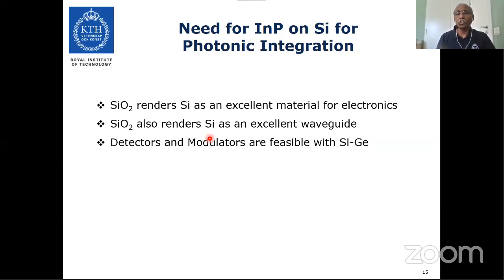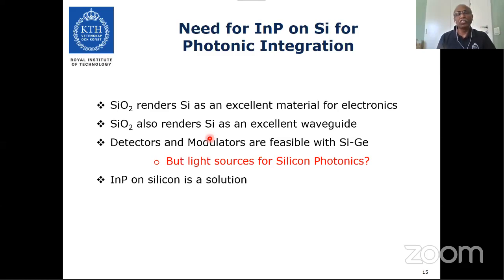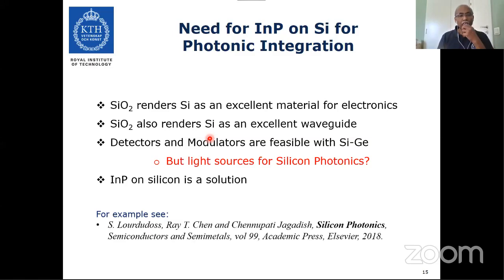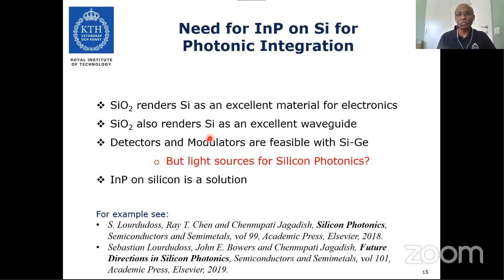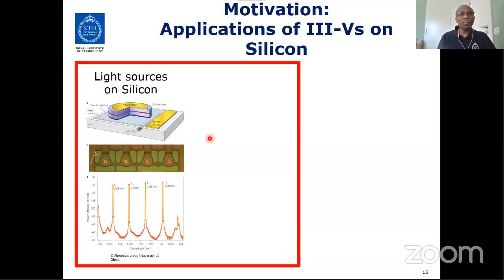The detectors and modulators are also feasible with silicon and germanium. But light sources for silicon photonics, if you want to have light sources on the integrated circuits, we do not have light sources on silicon. We cannot make them from silicon alone. So indium phosphide on silicon is a solution, or 3-5 materials on silicon is a solution, because 3-5 materials can produce light. Most of the 3-5 materials are direct bandgap materials, and silicon is an indirect bandgap material. You may refer to two recent books which we have edited on silicon photonics if you want to know more. So light sources on silicon are necessary.